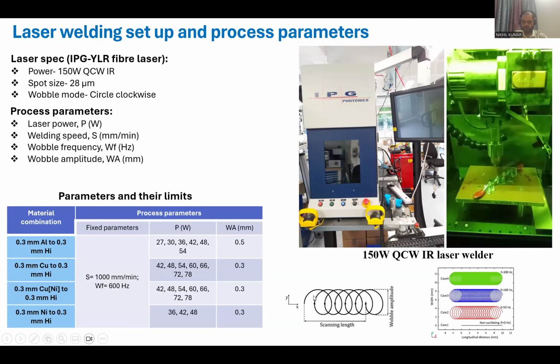So I have used the wobble mode or beam oscillation mode for welding these two pieces because they are conducting material. So the laser is not moving in a straight line. It is moving in a spiral this way. This is called the beam oscillation. So that's why there are two additional parameters added here. You can see the process parameters for this particular laser. One is the laser power, one is welding speed, and the third and fourth are the wobble frequency and wobble amplitude.